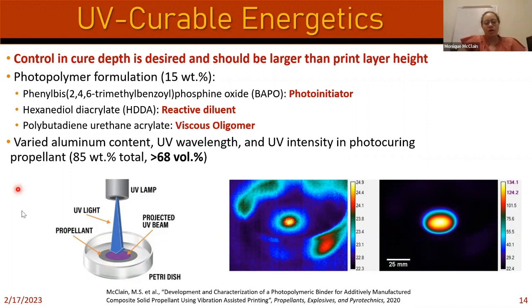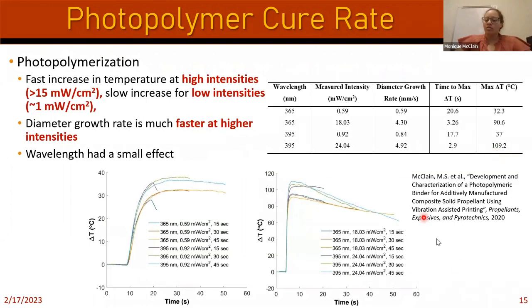In terms of measurements from this experiment, we also used an IR camera looking at the surface. We measured the temperature change from this curing process and looked at the overall behavior. As soon as we saw light being applied to that Petri dish, that would count as time 0. Then we would look at the maximum temperature change relative to the starting temperature. For example, this photopolymer reached a really high temperature, but we calculated the change in temperature, so this is more like a 110 degree change in Celsius. That's how we measured some of these features: how much time it took to get to that max temperature, what that peak temperature was, and so on. Here I have some examples of that.